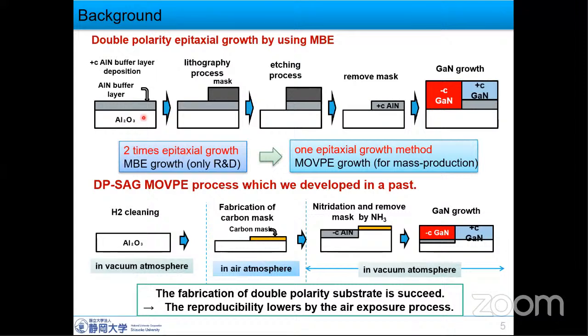After growing on the aluminum nitride buffer layer, QPM crystals are fabricated by dry etching and a gallium nitride regrowth process. So this method requires two epitaxial growth processes. Furthermore, mass productivity is low because the MBE method is used.